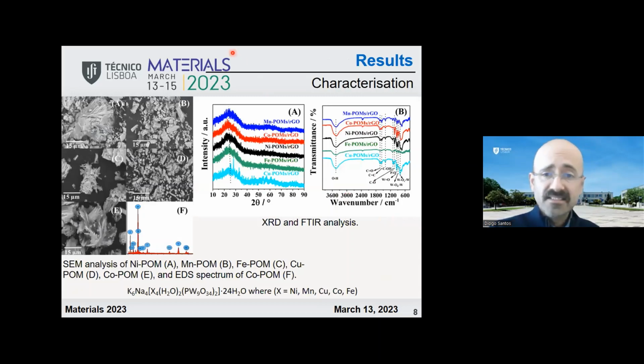This is the characterization of the 5 different transition metal POMs. This is the SEM analysis of the materials, and here is the XRD and FTIR analysis of the POMs with the RGO. So the final electrocatalysts that we tested, and this characterization showed that the materials were prepared as aimed.